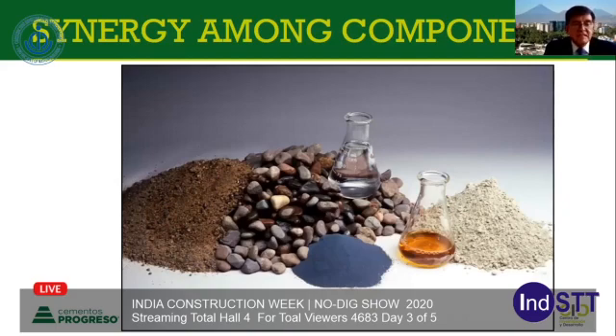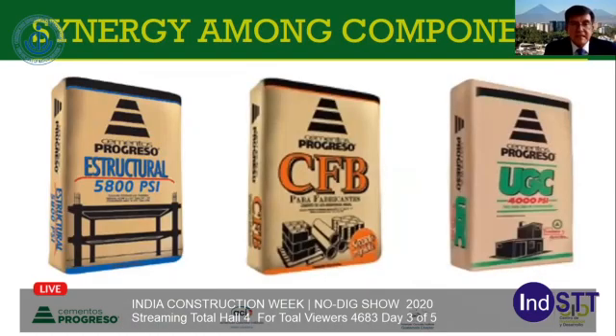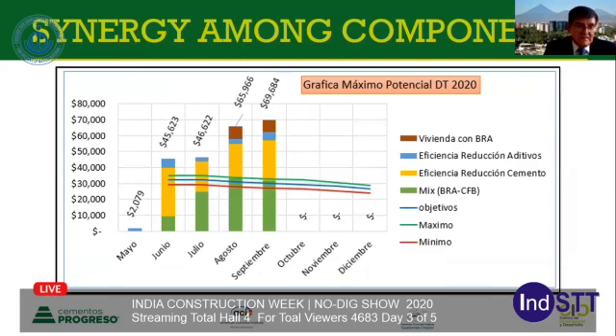So the other important source of cost reduction focuses on achieving synergies between components of the mixes. For example, the proper combination of different types of cement. We have several types of cement with different percentages of supplementary cementitious materials. In our case, it's natural pozzolan. Since we have lots of volcanic ash, that makes sense. Usually, the more SCMs that the cement has, the cheaper it is. Interestingly enough, we found out that we can achieve significant cost savings when we use a combination of more than one type of cement in our mixes, combining performance with price. So we have to make trials on this, but it pays off, as well as with other components, such as the type of admixtures. The perfect combination could get you huge savings.